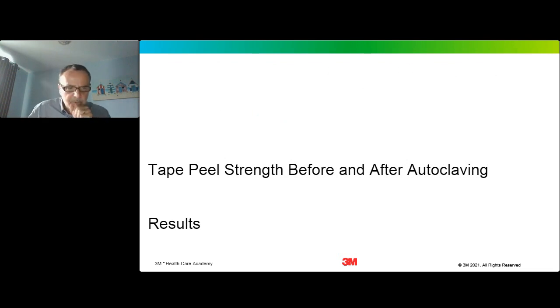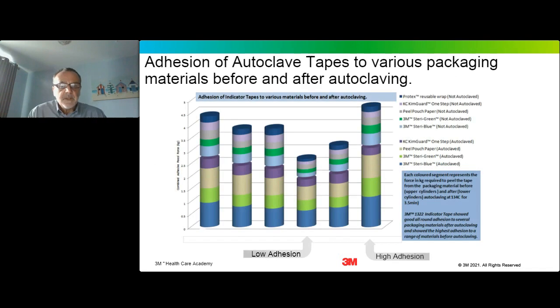If we look at the results of these peel strength tests, this slide is quite complicated, so let me try and explain it. It's showing you a summary of all the peel force measurements made during these tests. Each drum represents a different manufacturer's autoclave tape, and each colour segment within the drum represents the adhesion on a different wrapping material. The upper drums represent the peel force before autoclaving, and the lower drums the peel force after autoclaving. So let me just make some simple observations.